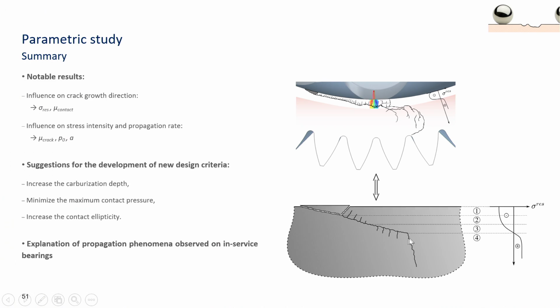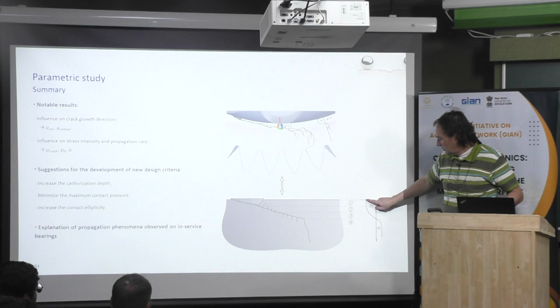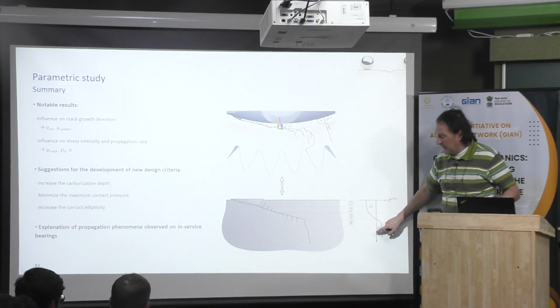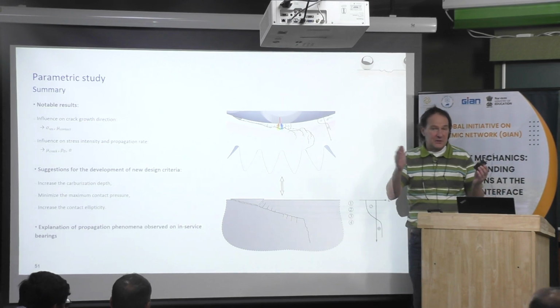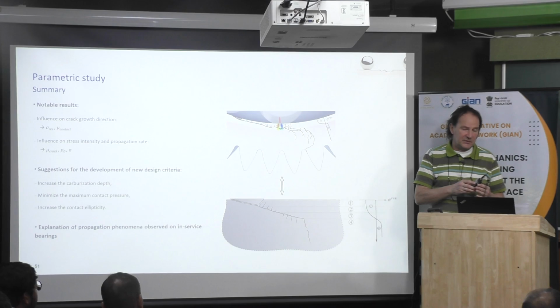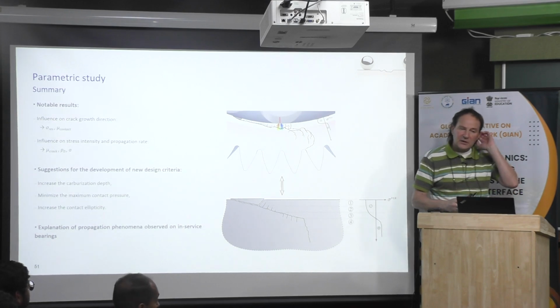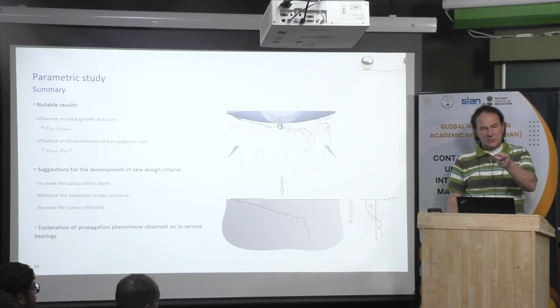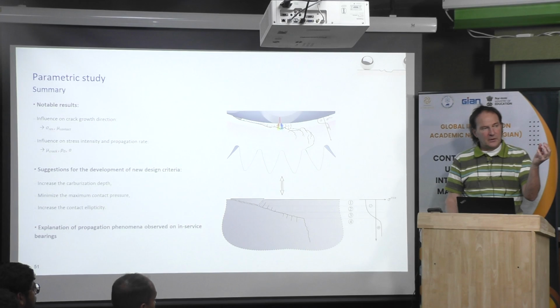Maybe I can go back to this slide. For example, you can manage to have a deeper area with compressive residual stresses at the surface. You can manage to reduce the bending of the gear, this type of thing. And they also had other solutions, it was in the video. They modified the trapping of the particles by using something magnetic with higher flux, with fewer particles they are able to detect a failure, things like that.